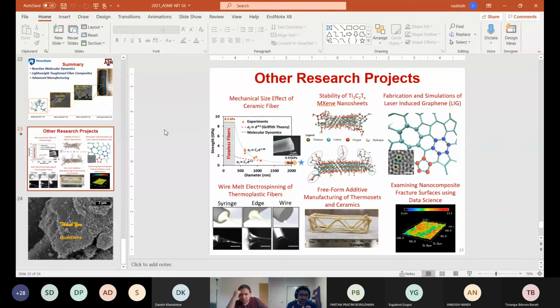The Achilles heel for this material is that it's not stable at room temperature. It basically disintegrates. Think about aluminum: if you have an aluminum surface, you develop a layer of aluminum oxide. Similarly, MXenes are reactive at room temperature. You can't just keep them on the outside. Graphene, you can put on a table, come back 5 years later, and it'll be mostly graphene. MXene, if you do that, disintegrates. So that's a very interesting area of future research where I plan to work.